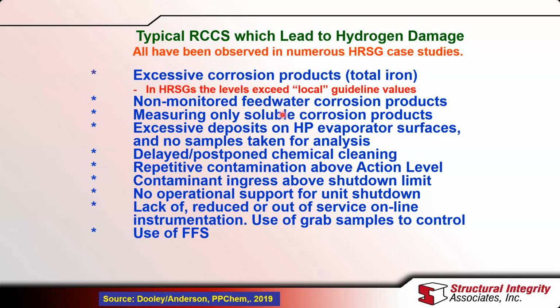Sometimes these corrosion products are not measured properly, and sometimes plants only measure the soluble part of the corrosion product. So that doesn't measure the total amount of corrosion products that are being transported. So these corrosion products flow into the HP evaporator, and they form deposits on the surface. And most often plants have not taken samples of the HP evaporator to be able to identify whether those deposits are great enough to cause hydrogen damage to take place. And there's a particular guideline for that, which I'll show you.